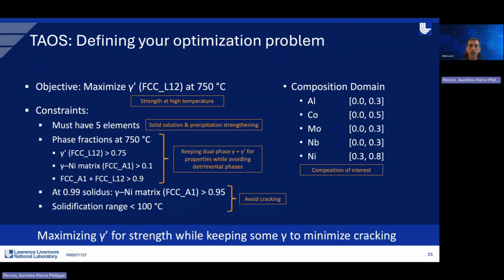And finally, for the cracking, you can say, okay, I don't know the melting point of my alloy, so I don't know the absolute temperature, but I can say that at 99% of the solidus, so relative temperature, I want my alloy to be 95% FCC, so really close to being single phase. And I want my solidification range to be below 100 degrees C. So with that, you define your optimization problem.